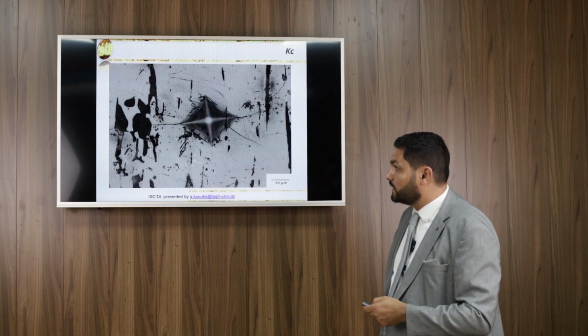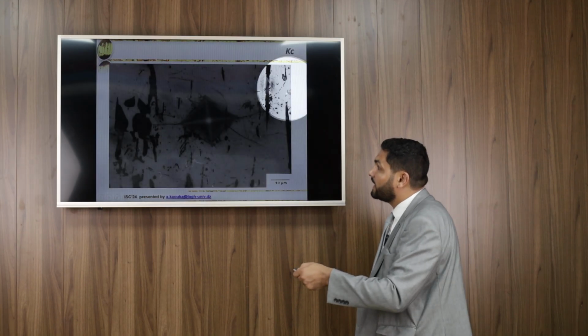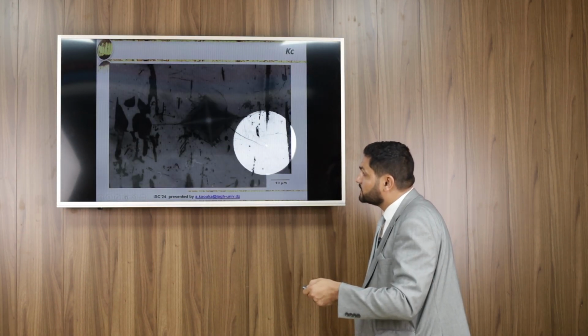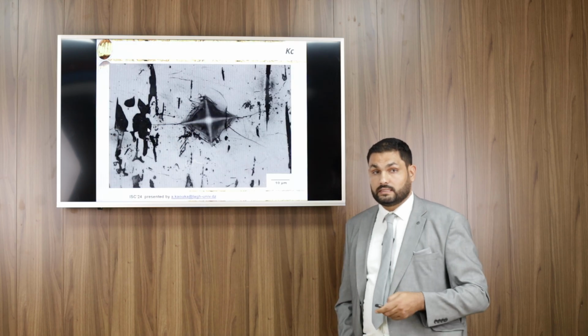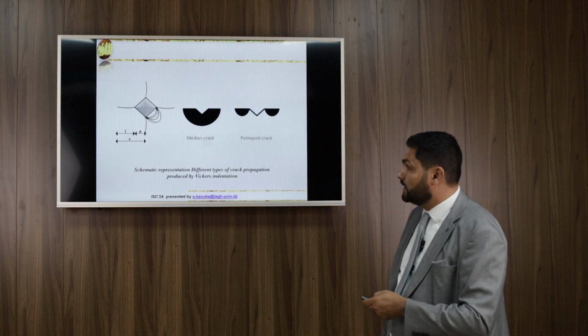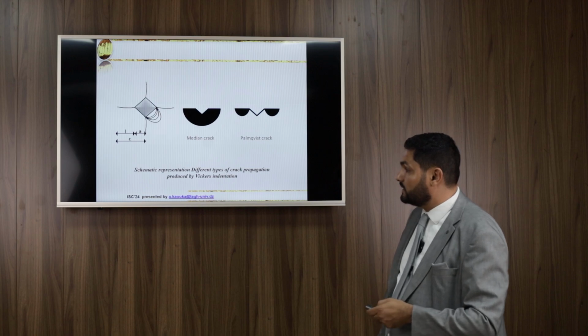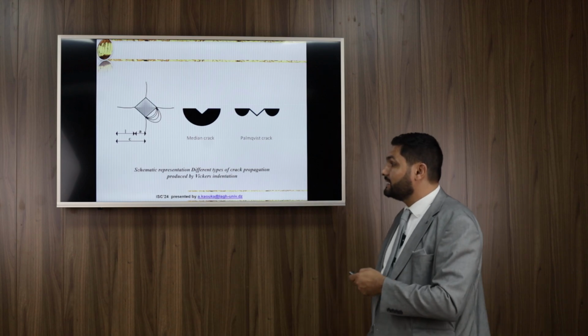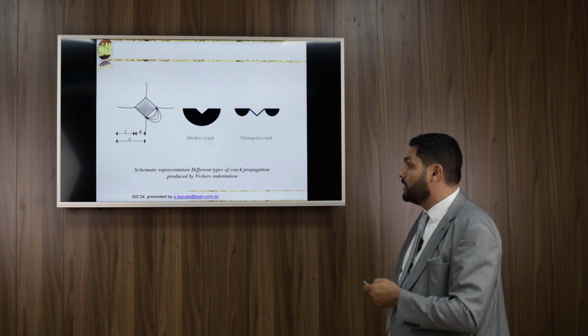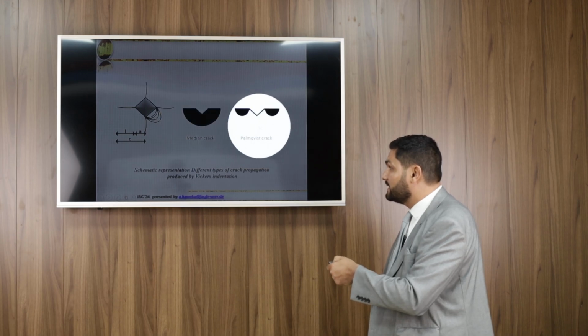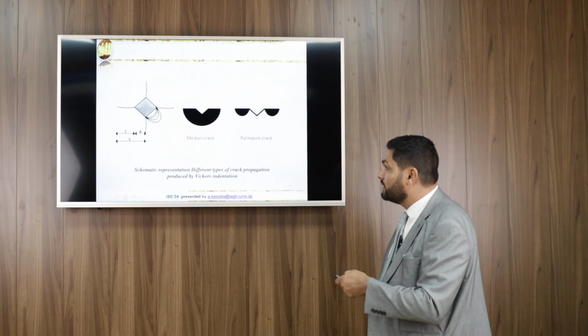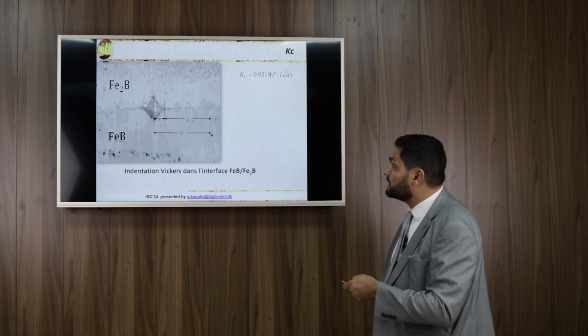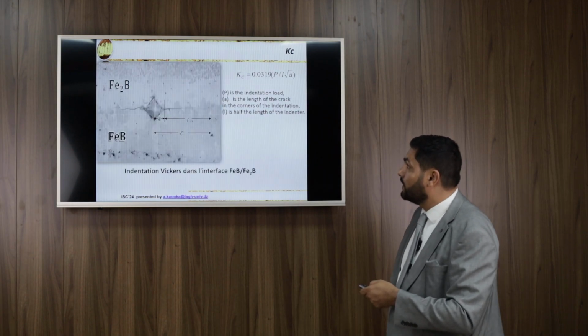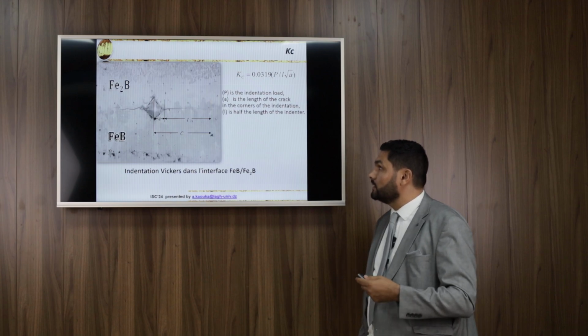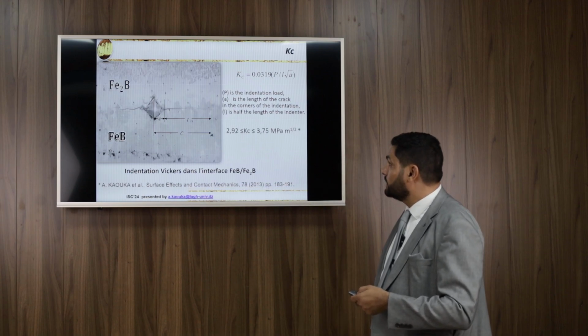For fracture toughness, when we do indentation, we measure the crack. This is this crack, or this crack. We measure the crack lengths L and C, to measure the fracture toughness of boride layers with this relation. This schematic representation shows different types of crack propagation: this is the median crack and this is the Palmquist crack. With this relation, we can easily measure the fracture toughness of boride layers, using the indentation load, the crack length, and the length of the indent.